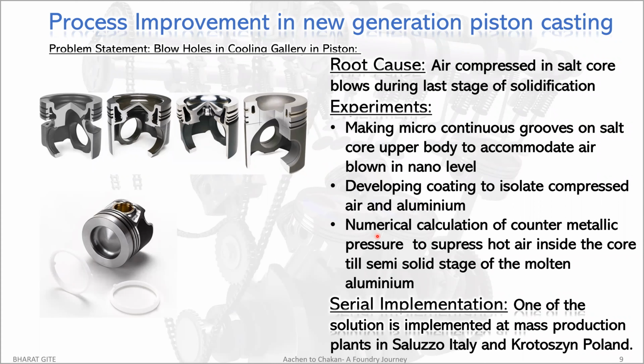So metallostatic pressure by increasing the riser or feeder height was also possible. But I calculated those meters and the riser was going up to 15 meters high, which is impossible for us to design. Hence, I came up with the idea that external pressure would be applied at the last few seconds of solidification to suppress the air inside. It was 100% successful, but due to technical problems and the serial production plant acceptability, we finally went with one of the solutions above, which I can't mention.